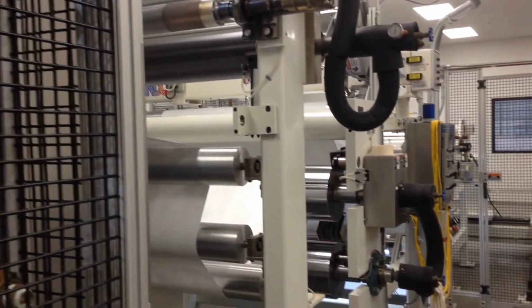Then it's going to go through a series of chill rolls. The adhesive formulation manufacturing is all done at elevated temperature, so it's a heated process. So we're laying down molten dots of adhesive onto the Tyvek in this case and getting them to set up and chill quickly. So Rick's going to talk about the other coating technology that we have at our disposal.